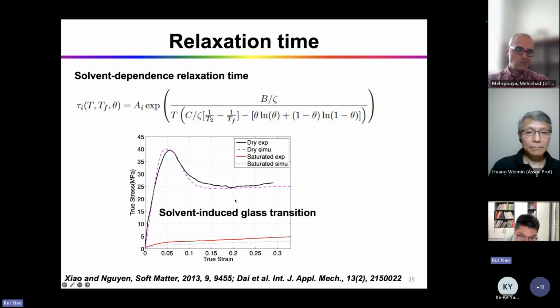So you can see we have this model - we have solvent concentration. With 3% solvent, the material became soft, but if we do not have solvent dry, it has glassy polymers. So we incorporate the solvent-induced glass transition.